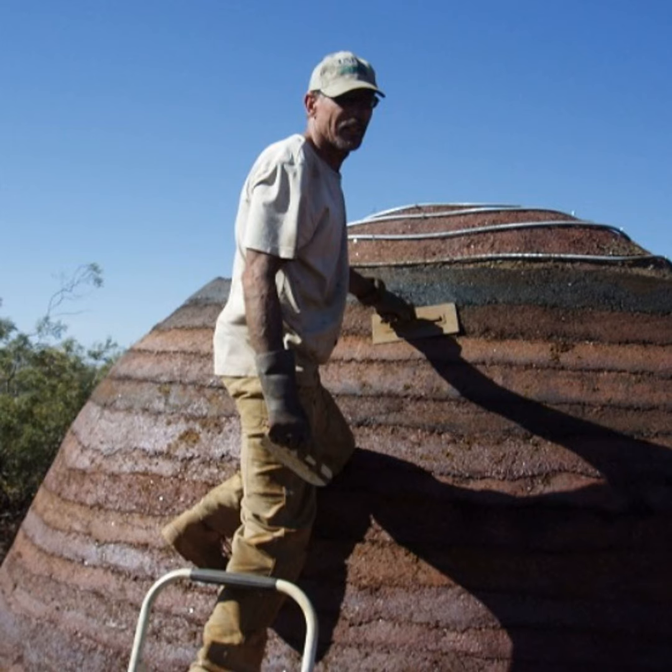So can Ferrock be recycled? Yes, it can be ground up. And typically there's enough metallic iron, the raw, pure elemental iron that we spoke of earlier, still in there to help trigger a secondary generation of a cemented Ferrock binder. Plus, all of the iron carbonate is reactivated and exposed and acts as a surface, a kind of seed crystal for growing more iron carbonate.